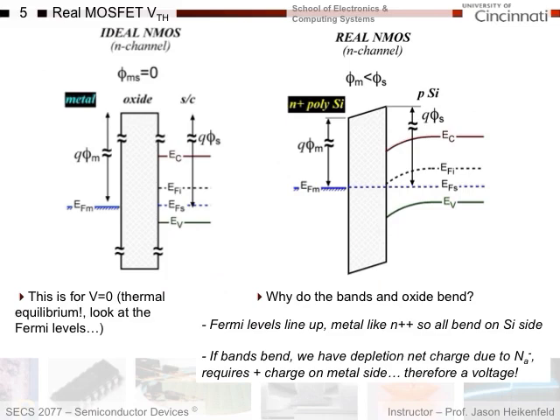Now, first thing we're going to look at for a real MOSFET in real-world parameters is that we're not going to have the case where the metal and the semiconductor have the same work functions. Before, we assumed they were equal, and so that gave me Fermi levels lining up, and I'm at flat band, I had no bending of the bands whatsoever. Okay? For a real MOSFET, we don't use a metal on the gate at all. In industry, they typically use a heavily doped polysilicon gate. Polysilicon means polycrystalline silicon. A perfect silicon wafer is single crystal, meaning there's the same crystal orientation all the way across the wafer. Polysilicon means it's highly crystalline, but only in local domains. But it has most of the same properties of a single crystal substrate. And so they can deposit this down, and it works quite well for MOSFETs.